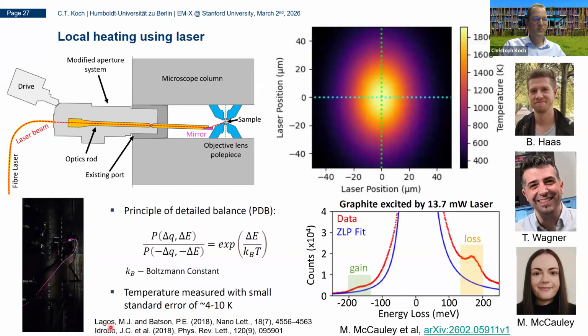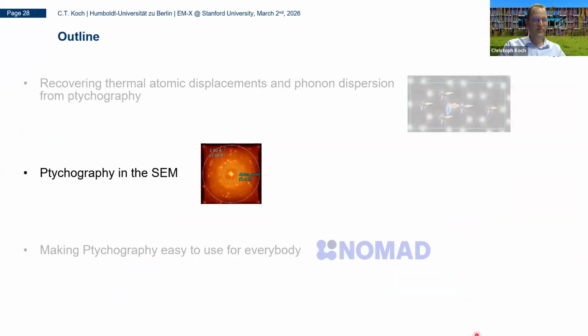There have been papers by Marine Lagos and Phil Batson, but also from Carlos Hidrobo, on really using this energy gain and the energy loss peak in EELS spectra of these phonon modes to actually determine the temperature without any reference. And so in this graphite sample here, they were able to actually heat it up to 2000 degrees and more, and actually convert also amorphous carbon to graphite and so on. But there's an arXiv paper where you may be able to find out more on this.